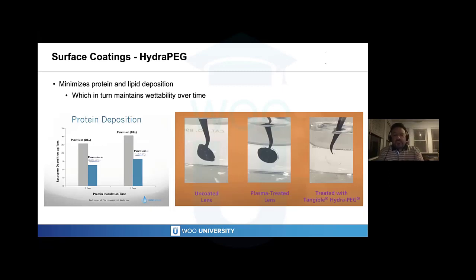As we look at the picture on the right, this is an example of a scleral lens that is dipped in a black colored lipid and then rinsed in liquid or rinsed in water. And when we have a lens that is not coated or plasma treated, you see that that lipid does absolutely stick to the surface of the lens, because even as we rinse that lens in liquid, the black lipid stays attached to the surface. However, when that lens has been coated with the polyethylene glycol surface treatment mixture, it resists the deposits from sticking to the surface.